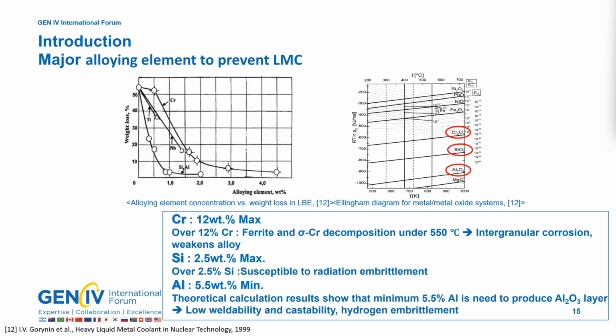The major alloying elements in steel are silicon, aluminum, titanium, niobium, and chromium. These elements show protective results in an LBE environment. Among them, chrome, silicon, aluminum are the most effective elements, as shown in the Ellingham diagram.